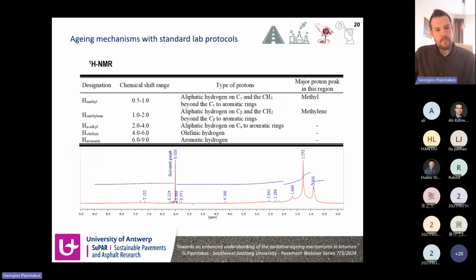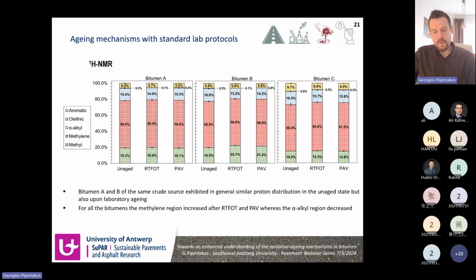Complementary, we used proton nuclear magnetic resonance, or HNMR. HNMR can be used in bitumen as a kind of chemical fractionation besides the polarity-based fractionation of SARA. At the bottom, you can see a typical spectrum of bitumen, dissolved in deuterated tetrachloroethane, and the areas were used, of course omitting the solvent peak of tetrachloroethane, in 5 different proton regions of methyl, methylene, alpha alkyl, olefinic, and aromatic. And these were studied in terms of aging with RTFO and PAV.